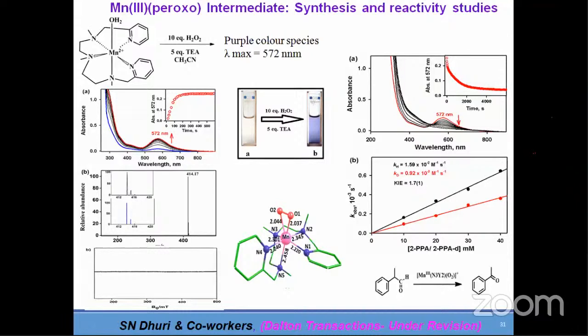So we tried the reaction with the deuterated substrate. When we did that, we got a KIE value between the deuterated substrate and the normal substrate of something like 1.7. Of course, we need to do some more reactions over here and check whether it is really 1.7. Some more experiments are to be done. This work we submitted to Dalton Transactions, and it has come back for revision. So that's why I said some of the work is to be incorporated in the revision.